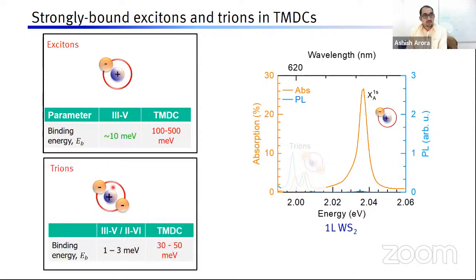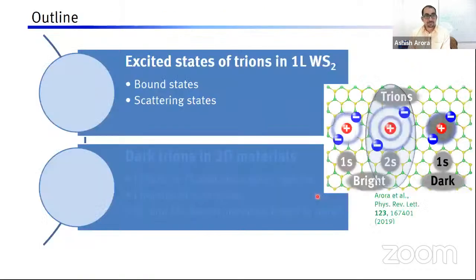If we add an extra electron, we get a trion, and we find that the binding energy of trions is also much larger, an order of magnitude larger compared to the III-V semiconductors. Therefore, we should be able to see these trions at elevated temperatures now. Now, these trions also appear strong in the absorption and in luminescence spectra below the exciton by an amount equal to the binding energy of the trion. So here, orange is the absorption and blue is the photoluminescence spectrum of tungsten disulfide film at low temperature, at around 10 Kelvin, in this work.